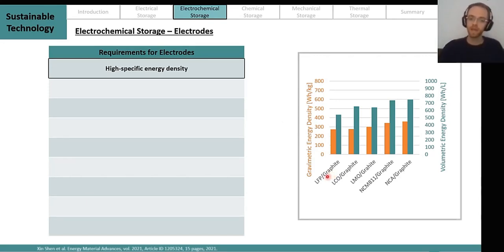What you see now is that depending on the materials, like here we have a combination of LFP as our cathode and graphite as our anode side, which will be similar for all of these cells, and LCO, LMO, NCM, and NCA here as the cathode. We do notice that we have a clear variation in our gravimetric and volumetric energy density. Unfortunately, for LFP, which only uses iron, we notice that we have the lowest gravimetric and also the lowest volumetric energy density, which is unfortunate, but still renders it usable for certain applications where you don't mind so much about the weight or the volume of your storage.